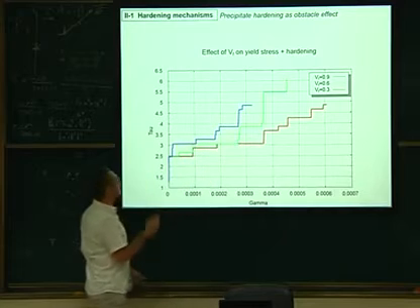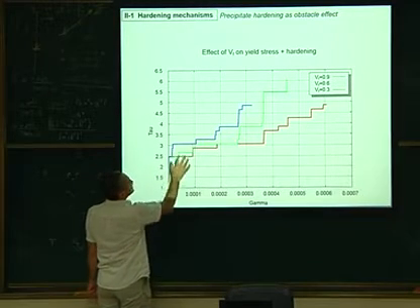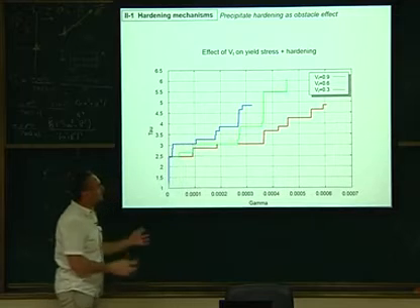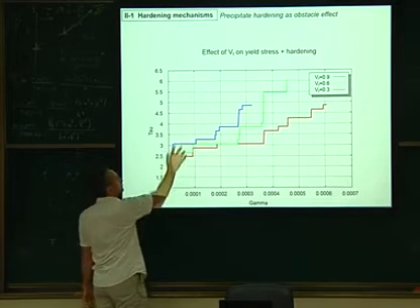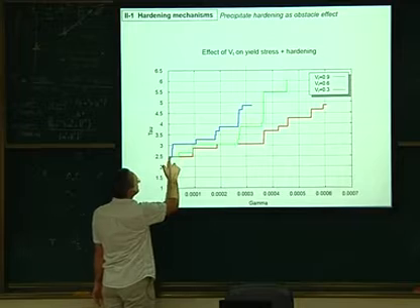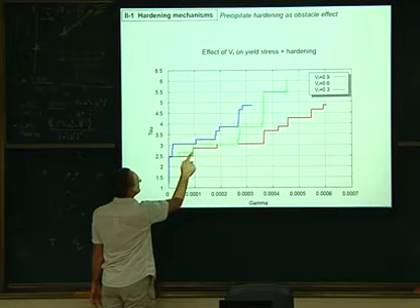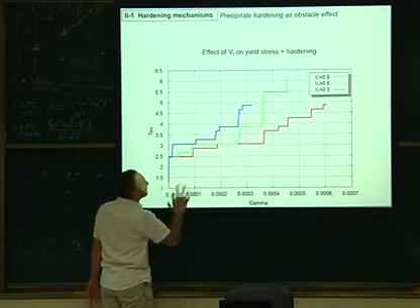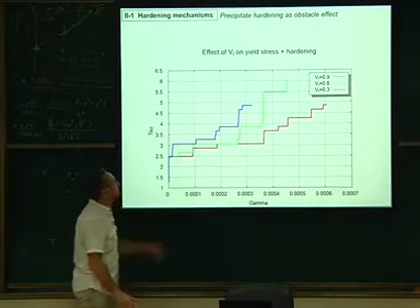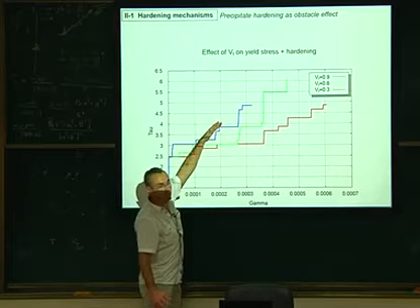So here you see 2 things. First, you can see that you have a yield stress, which is not much depending on that. Here, at least, there is not a big difference between the 2 yield stress, just because they do not encounter here, I think, no, it's here, yes. So here it's the initial stress. So this is the shear stress we should compare, but they are comparable. Let's say this is not a big deal. There is not a big issue about the yield stress, but there is a big change in the hardening slope.